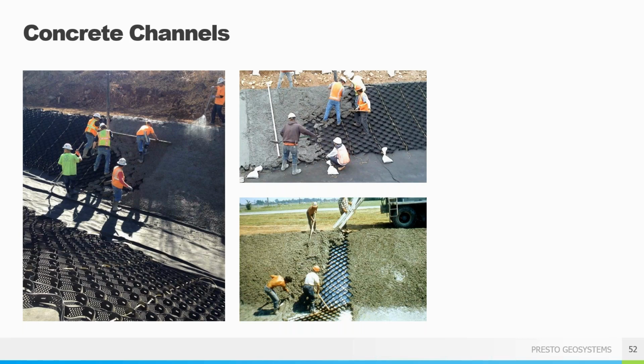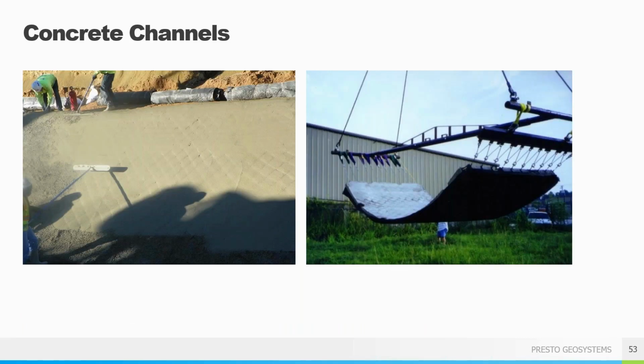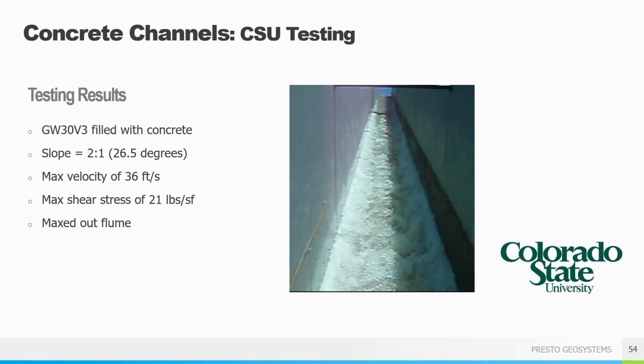Once anchored in the channel, the GeoWeb allows concrete to be pumped or poured right into the cells. And again, we screed it right to the top of the cell walls. Notice the flexibility of the concrete-filled GeoWeb panel in the photo on the right. It's not going to crack like poured-in-place concrete will. Again, the system was tested at Colorado State with very impressive results. Our mid-sized cell, just 3 inches deep, was able to withstand 36 feet per second and 21 pounds of shear. And we actually didn't even fail the system, but rather maxed out the flume.